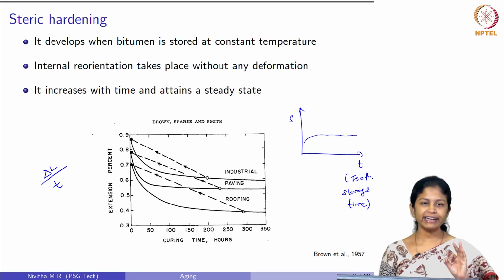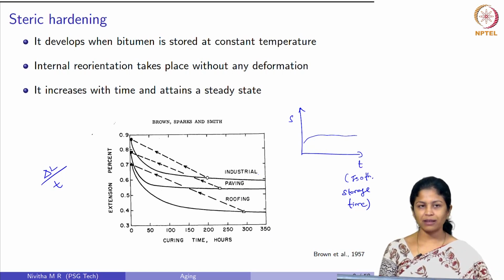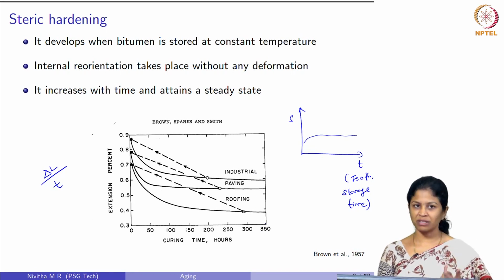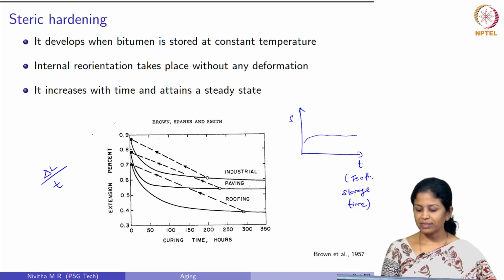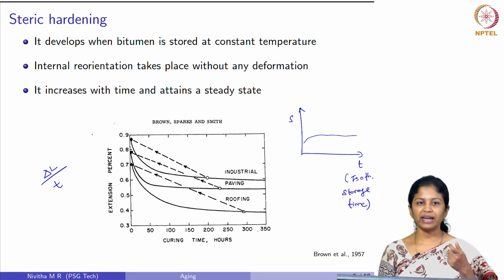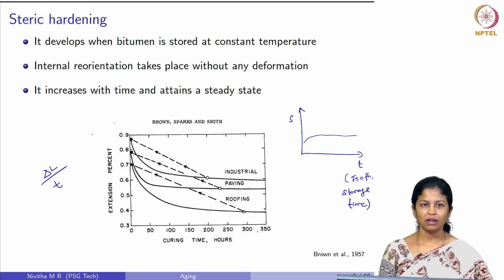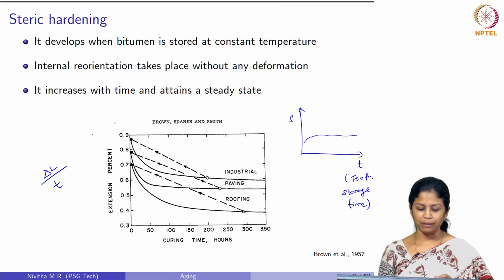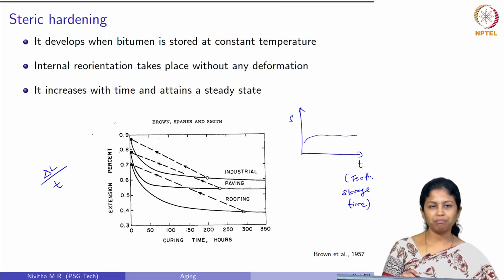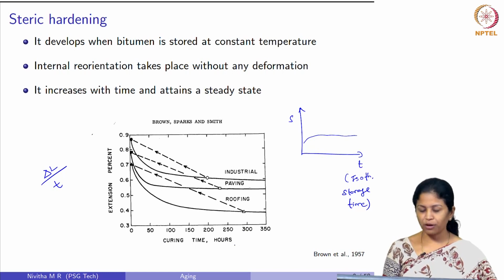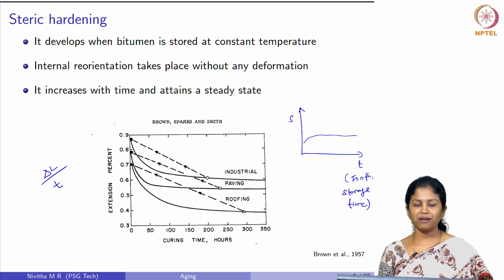They have taken 3 different types of bitumen. One is an industrial bitumen, second one is a paving grade bitumen, third one is a roofing grade bitumen. Each of them was subjected to different loads. The industrial and roofing bitumen were subjected to 1000 gram of load for 1000 seconds, whereas the paving grade bitumen was subjected to 500 gram of load for 500 seconds. To normalize the effect of time applied, they calculated this delta L by T. That is this extension percentage, and then this is the curing time. Curing time means the time period for which the material was stored at isothermal temperature.